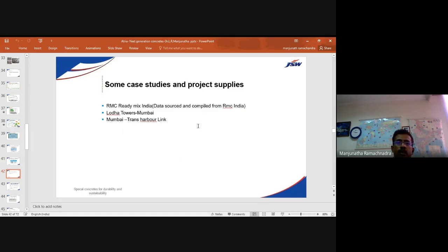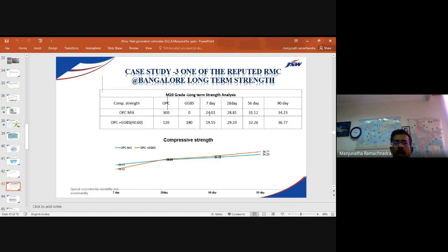Similarly, we have compiled data for many companies. So you can use 60%. This is a blended concrete. This is what I have done: 60% GGBS, 40% cement. You can see the improvement in the compressive strength compared to OPC mixes. It gave on 90 days 34.23 MPa.